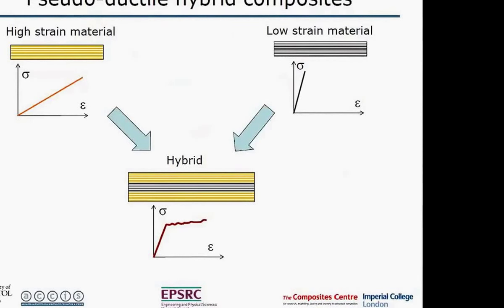So, pseudo-ductility in hybrid composites. In a hybrid composite, you start off with a high strain material, for example, glass, which has got a lower modulus but a higher strain to failure, and then you have a low strain material, which might be carbon, which has got a higher stiffness but a low strain to failure. You put them together to form a hybrid, then if you do it right, you can get this sort of stress strain characteristic like that, whereby you get an initial elastic response, and then you can get a plateau type behavior as this pseudo-ductility mechanism comes in.